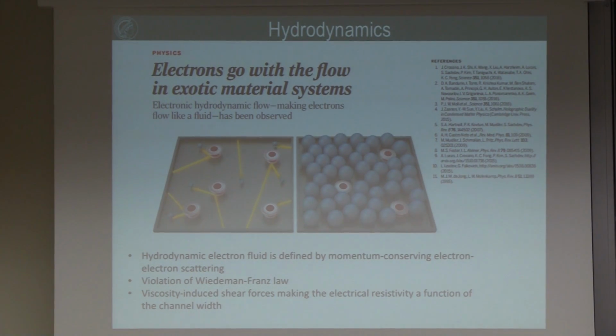So what is the idea behind the hydrodynamic flow? So if you have electron gas, we always assume Drude-like behavior, which is not reality, we know also, that the electrons get scattered at the nucleus, but if the electrons behave more correlated like water molecules in water, so they don't see the nucleus, and the electron-electron scattering dominates the process, and you don't see the electron-phonon scattering. So then these are the predictions, so that you have momentum conserving electron-electron scattering, you see a violation of the Wiedemann-Franz law, and you see this viscosity-induced shear force making the electric resistivity a function of this channel width.